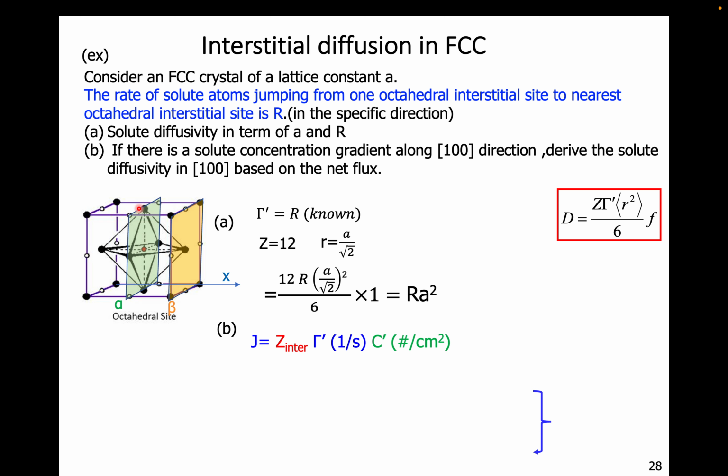So here is 2, this area 2 and 2. So each plane turns out all of them have only 2 atoms per A square, identical area density. So it turns out I can use Fick's first law. So the area density, all planes are 2 divided by A squared.